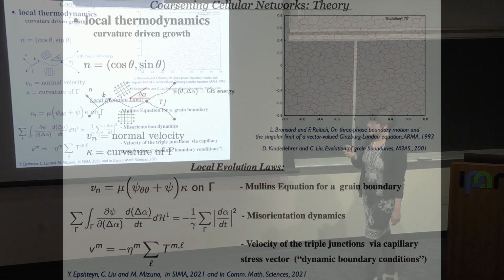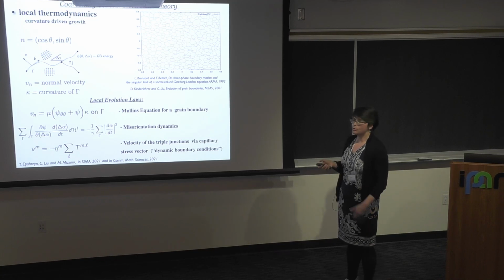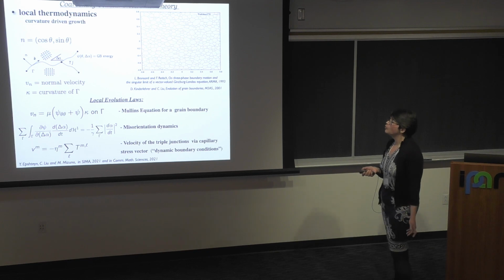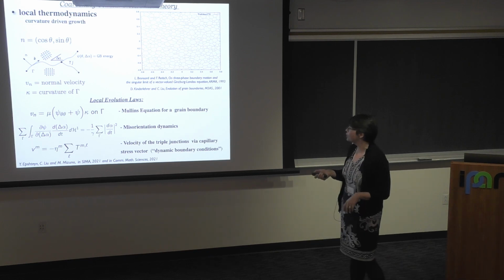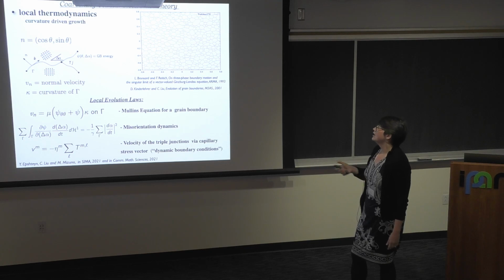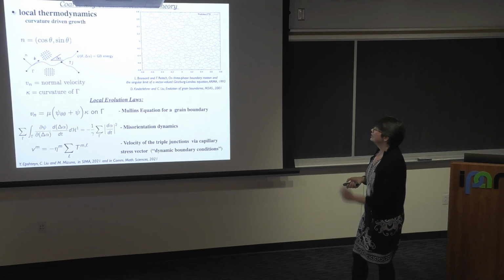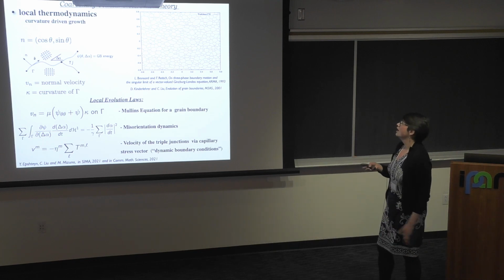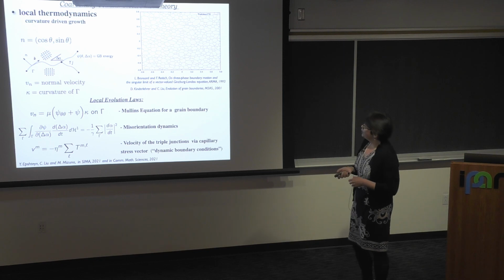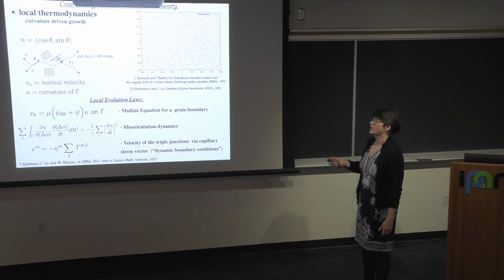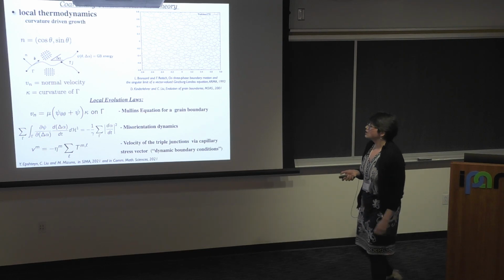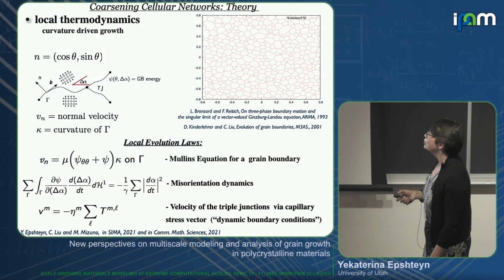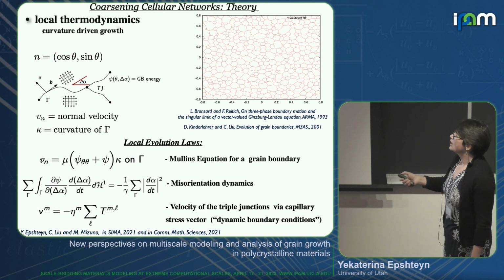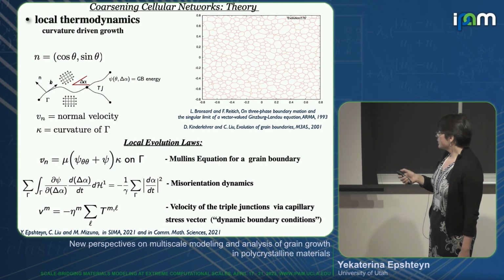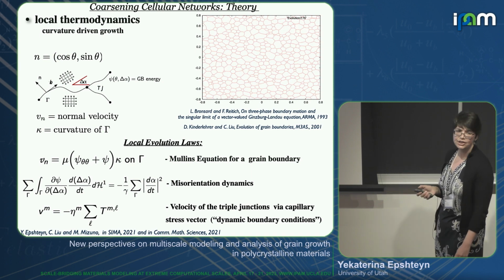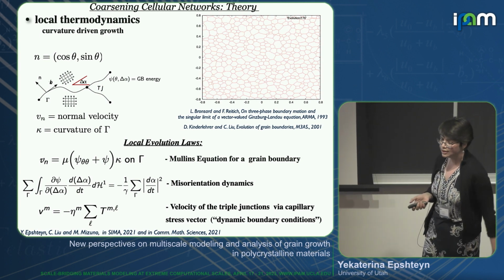So for dynamics of grain boundaries, we assume a classical assumption, which is actually what most mathematical literature is really focused on, and I presented here some of the relevant work on curvature-driven growth, on modeling polycrystalline materials. Of course, the literature is extensive, but one of the classical assumptions is the curvature-driven growth, and namely evolution of the grain boundaries according to what is known in material science literature as Mullins' equation for a grain boundary.